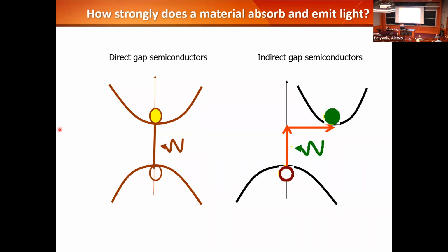So when you have a direct gap semiconductor, it absorbs and emits light with much greater efficiency than when you have an indirect gap transition, where the bottom of the conduction band and top of the valence band are not aligned. So there's a momentum mismatch, typically relying on a phonon to participate to compensate for that momentum mismatch. Therefore, although the van der Waals coupling is very weak, it was sufficient to change the band structure from an indirect gap to a direct gap. So going down to monolayer, you see a dramatic increase in light emission efficiency.